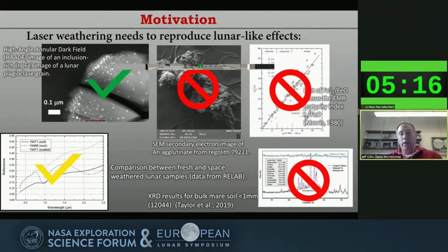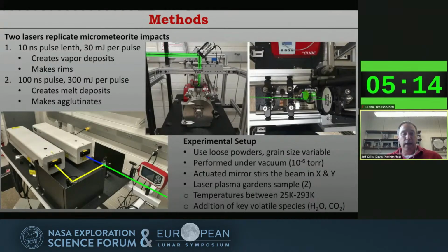So our motivation was to add a second laser. For typical lunar space weathering, we use the short pulse, as I mentioned before, which is a 10 nanosecond pulse length. That's about 30 millijoules per pulse. And this creates a lot of vapor and makes rims on materials. But what we've added is a longer pulse, a 100 nanosecond pulse, higher energy at 300 millijoules per pulse. This creates more of the melt deposits and makes agglutinates.